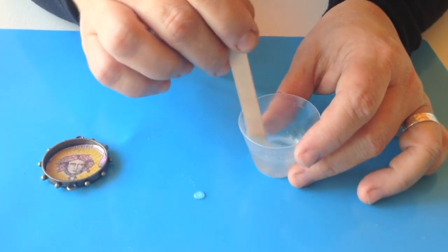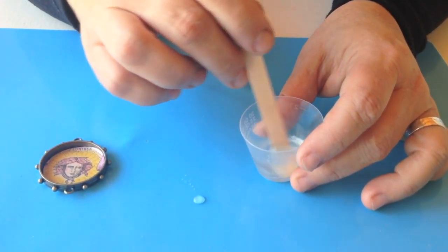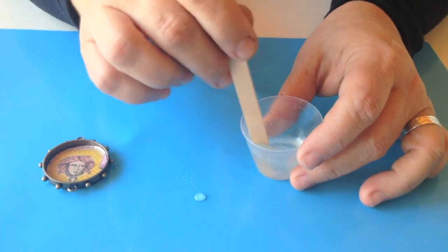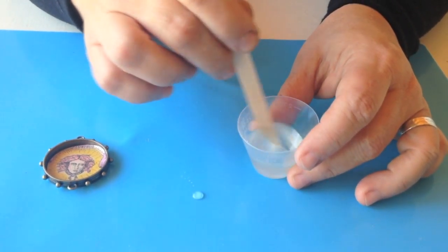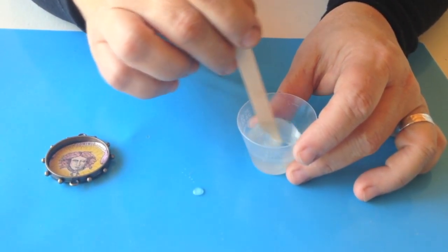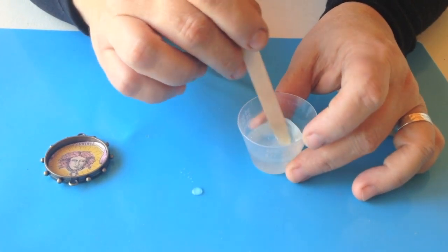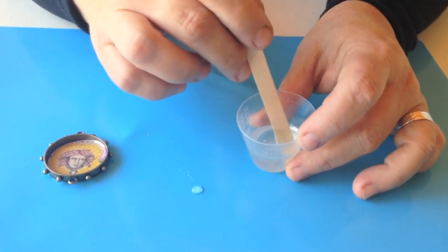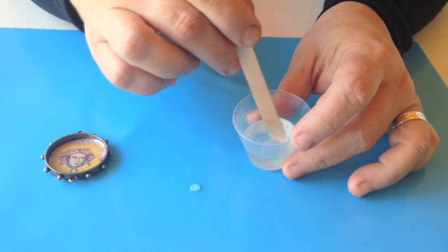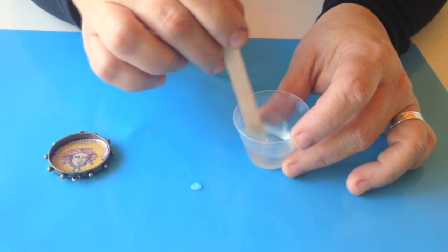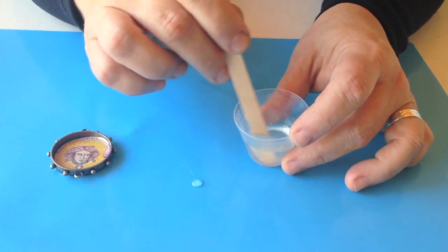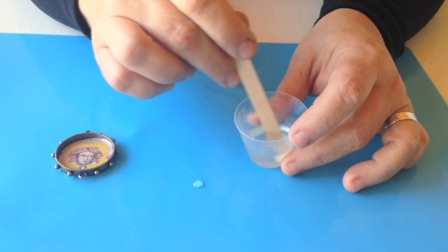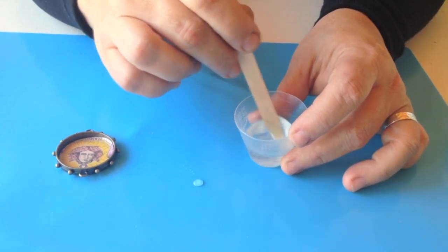Now you want to mix this gently and thoroughly for about one minute. The reason why one minute is because I'm mixing up only a half of a cup. If you're going to use the entire plunger and you go all the way to the top of this, you're going to want to mix about two minutes. It's important to mix gently. You can whip your resin if you mix too fast and too quickly. So gentle stirring for about one minute.